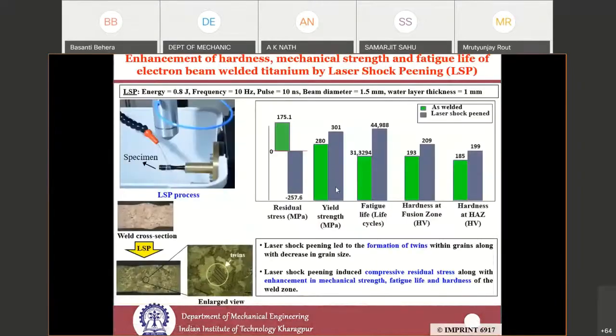Recently, we tried to improve the fatigue life of electron beam welded titanium welding by laser shock peening. After welding by electron beam, when you test the surface, you get tensile stress. But after laser shock peening, you get compressive stress. With this, the yield strength has increased, fatigue life has increased, and hardness of the fusion zone and heat-affected zone has also increased.